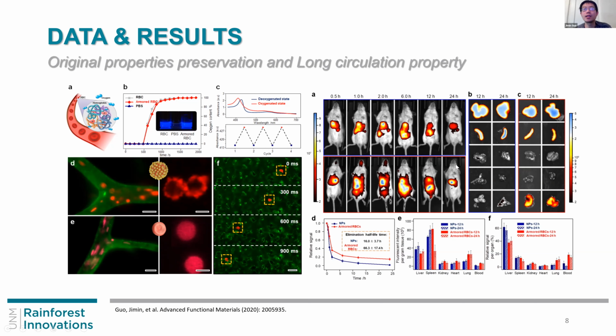So this is our mice study. We can see that if we directly inject the nanoparticle itself, the circulation half-life is only about 16 hours. But if we load it on the red cell, it becomes 66 hours, which is at least 4 to 5 times compared to the nanoparticle itself. Another interesting thing during our injection is that we can see accumulation in the lung. This is also interesting because most nanoparticles don't have this long accumulation property. So our system also benefits nanoparticle delivery in this case.